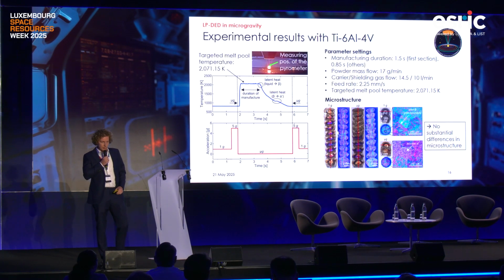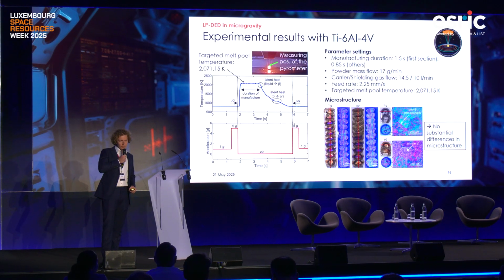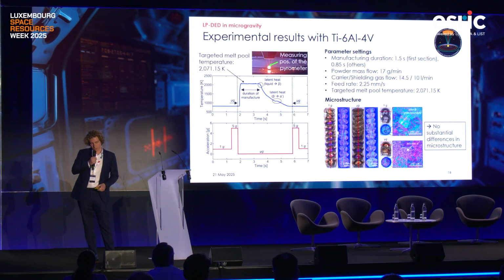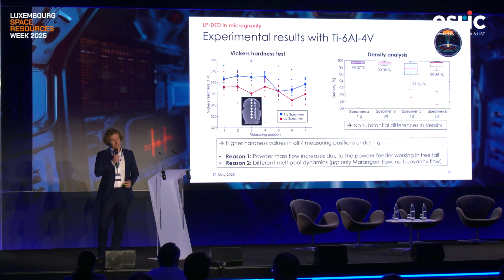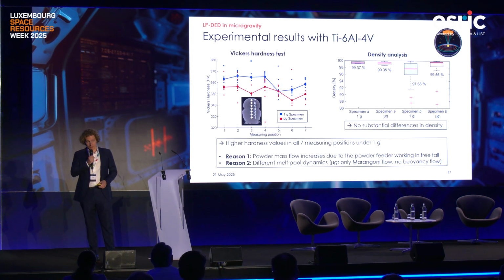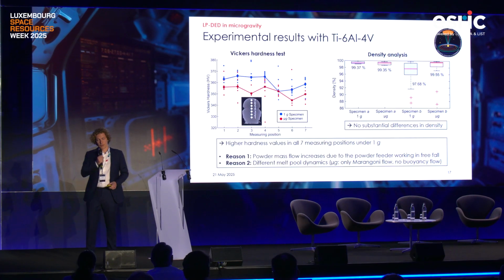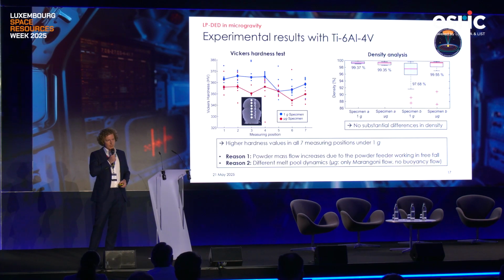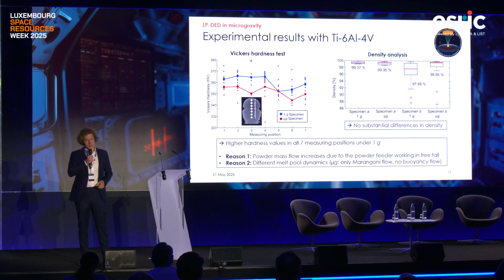Then on the right side, you can see the specimens. We manufactured specimens under microgravity and under 1G with identical parameter settings, and after it we compared the specimens with each other. So in the microstructure we have seen no substantial differences. Also, we have done some density analysis via CT scans, and there, again, no substantial differences. We have done some Vickers hardness tests, and there we have seen a higher hardness value in all the 7 measuring positions.